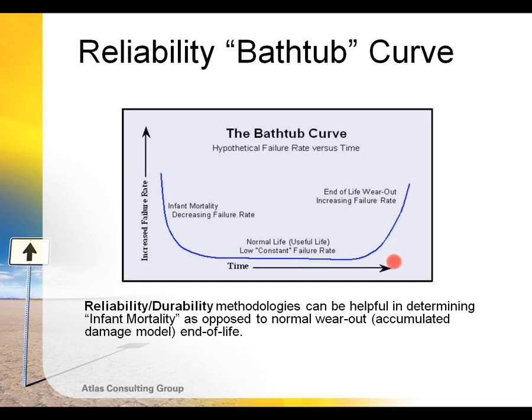We may have a residential hot water heater for your home. We may have some early infant mortality failures if there were some manufacturing issues or installation issues even. Then during its expected 5 or 10 or longer lifetime, it should perform relatively worry-free and with very, very few failures until eventually the heater becomes worn out, becomes corroded on the inside, and then we have an increasing number of failures, etc. So this is the bathtub reliability curve.